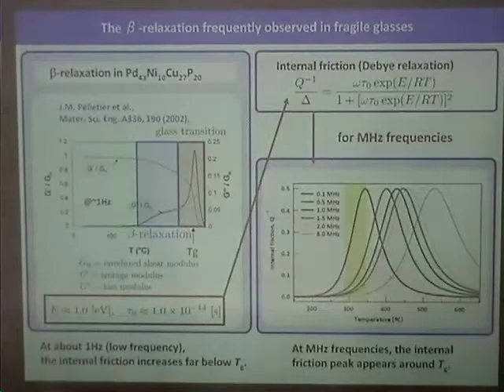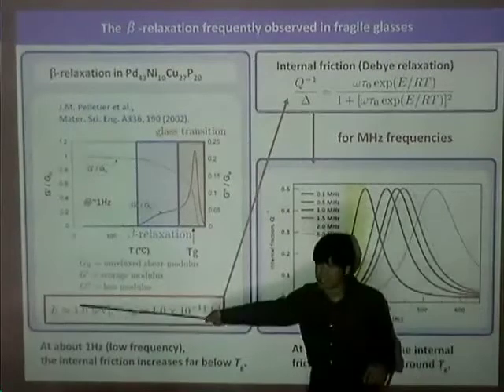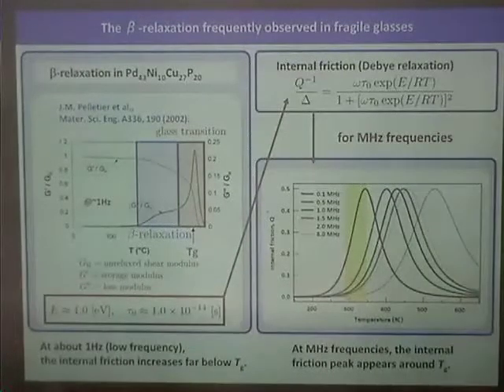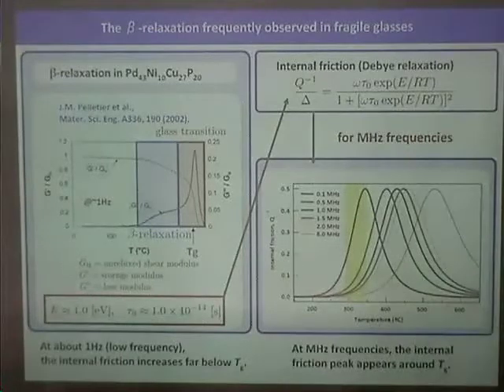Usually, in the case of alpha relaxation, the activation energy is probably 5 or 10 electron volts, for the whole process. One electron volt is not unusual; this is typical, for example, of atomic diffusion in crystals. Yes, one electron volt per atom, or two or three, depending on the process. In the case of interstitial diffusion, the activation energy is almost this value.